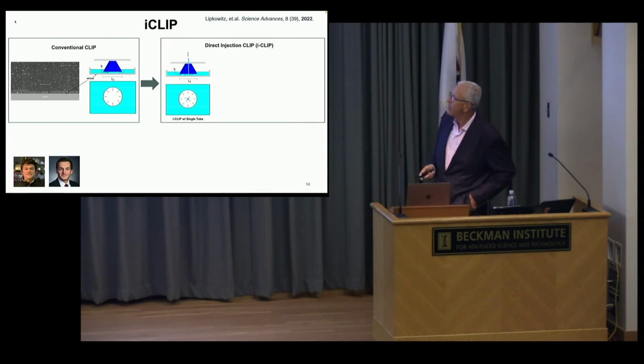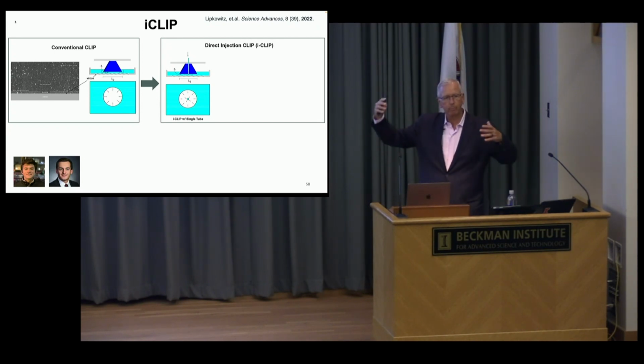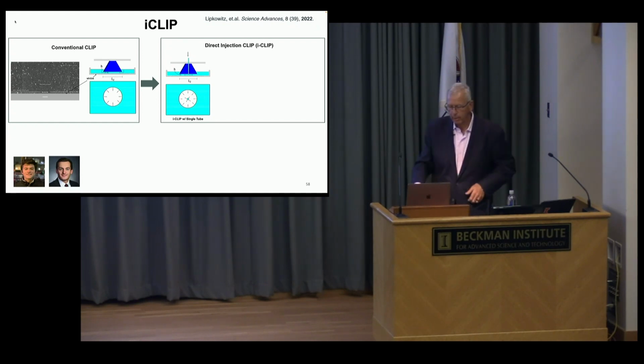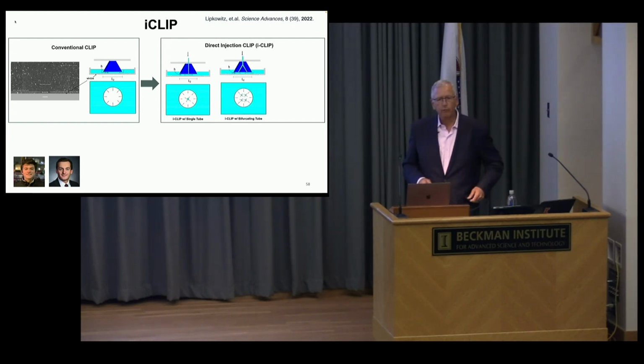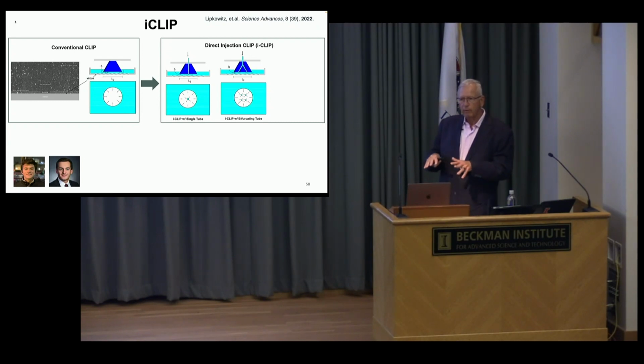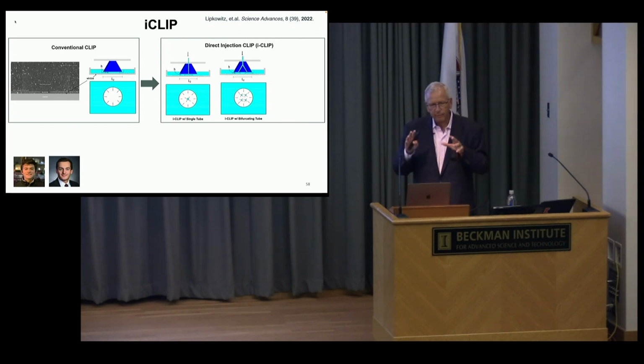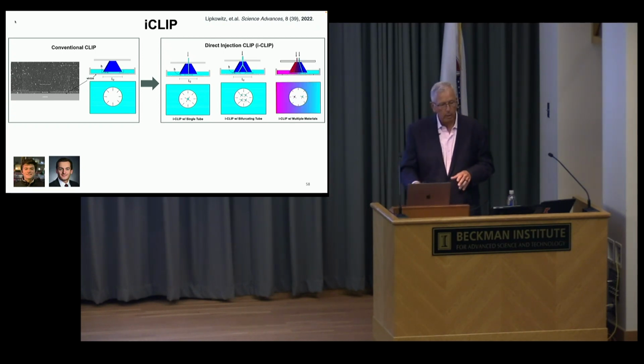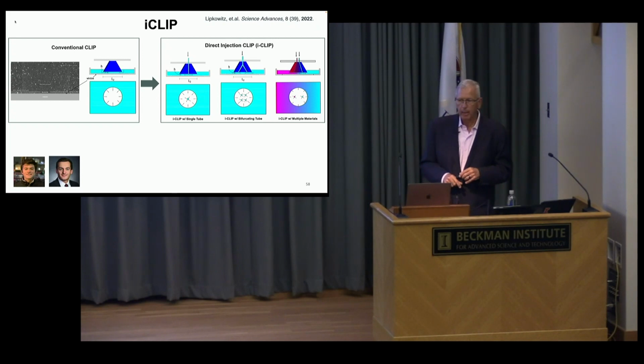So we've envisioned a process that now uses a mechanical injection of liquid through the platform, through a microfluidic channel that's dynamically created, and it goes into the gap. So now we can push liquid, not rely on atmospheric pressure and suction, like drawing liquid up a straw, but we're going to mechanically push liquid into that gap. And you can imagine you can design all sorts of innervated fluidic channels into the part and distribute it based on a lot of different criteria. And you could also imagine putting different liquids into this region.